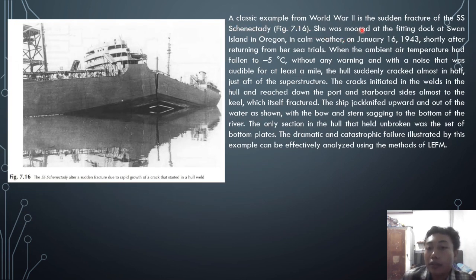As a classic example, consider the Schenectady fracture of the SS Schenectady, Figure 7.16. She broke apart at the fitting dock at Swan Island, Oregon, in calm weather on January 16, 1943, shortly after returning from sea trials, when the ambient temperature had fallen to minus 5 degrees Celsius. Without any warning, with a noise audible for at least a mile, the deck suddenly cracked almost across the hull, just aft of the superstructure, and settled down to the port and starboard side almost to the keel, which itself ruptured.